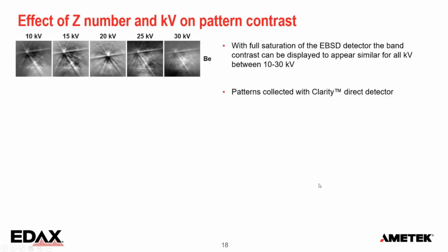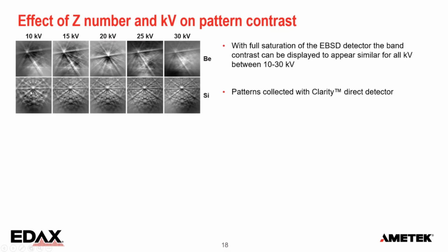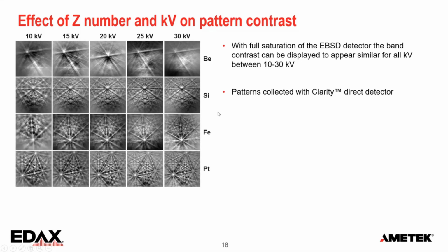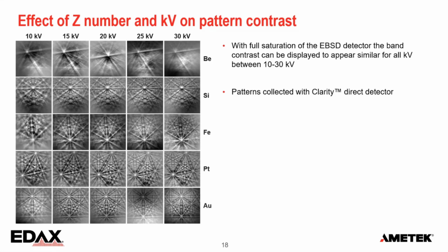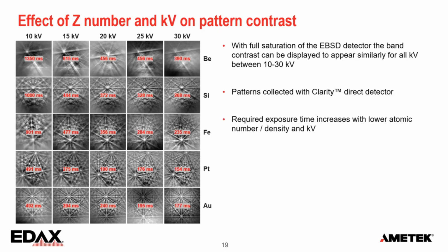Now, if we look at the patterns, when we just fill the entire well depth of the sensor, we can get good patterns everywhere. So it's beryllium, silicon. You can just see the bandwidth changing, very wide at 10 kV to much, much narrower at 30. But the contrast doesn't change too much. So this is after the normal background correction and image stretching that we always do. But the difference, again, is in the exposure time that you need.